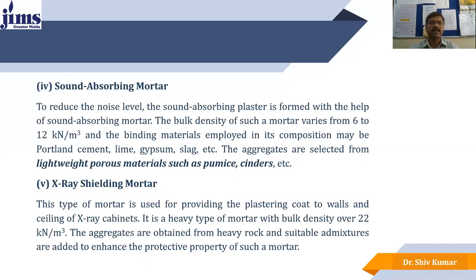X-ray shielding mortar is used to provide a plaster coat to walls where x-ray cabinets or x-ray procedures are conducted. It is a heavy mortar with bulk density over 22 kilo-Newton per cubic meter, and the aggregates are heavy, derived from rocks. Suitable admixtures can be added to enhance the protective properties of this mortar.